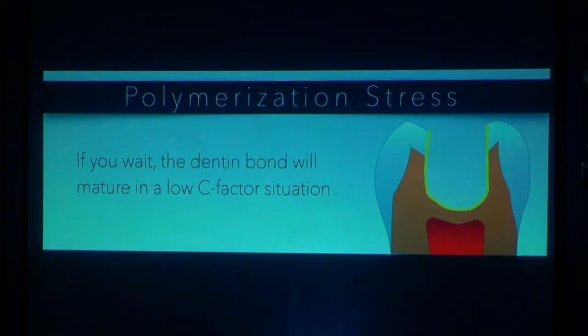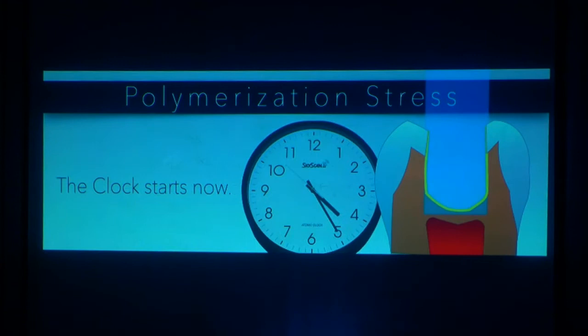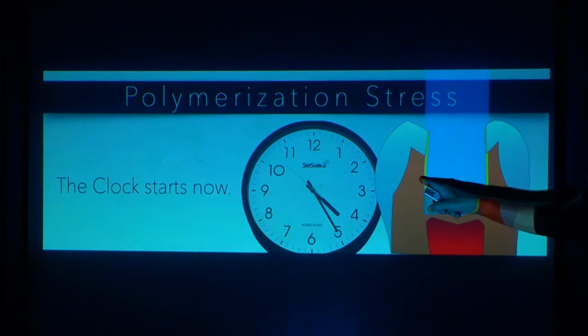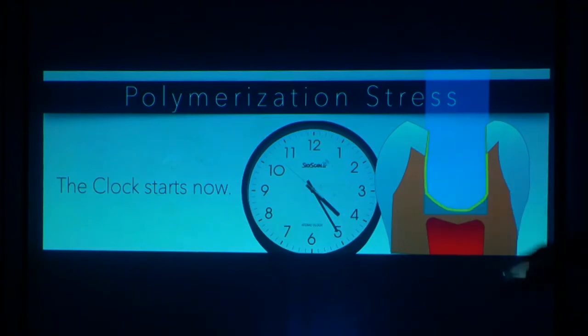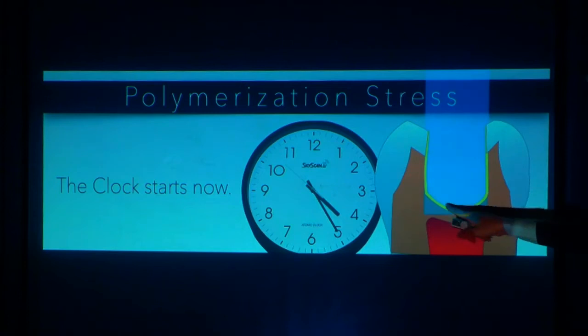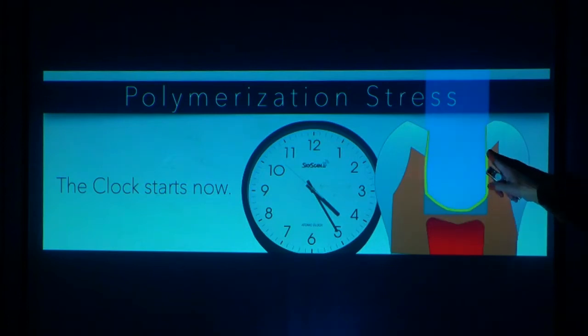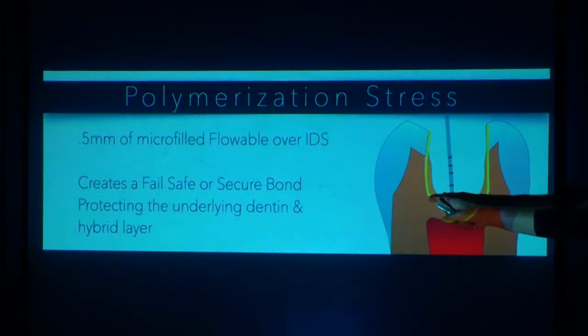So now let's go to the next step. You put the polymerization light on. If you wait 5 minutes from this point to get to a thickness of composite that connects these two sides of the wall, then this immediate dentin sealing matures in what it thinks is a flat surface. So this high C factor potential is limited because the layers in the initial polymerization curve are low. So we do our resin coating.